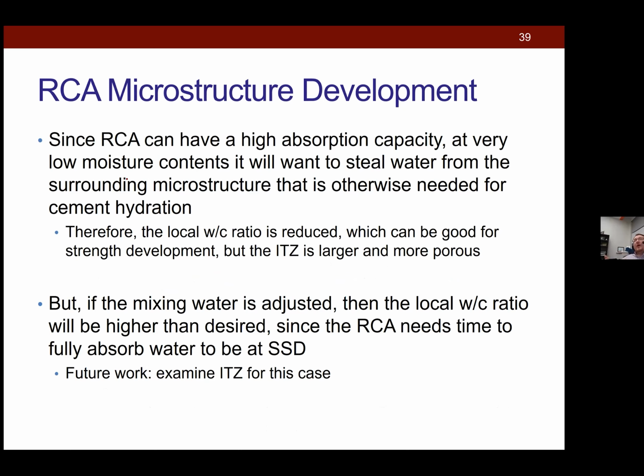Okay. The other problem is if, let's say, your RCA is completely dry, right, and it wants to absorb, let's say, 9% moisture. If you mix that RCA dry into your concrete and then adjust your batch water, the problem is RCA doesn't absorb all that moisture that quickly. Okay, so studies have shown that it might take 24 to 48 hours for RCA to become fully saturated. So it's kind of a useless method then to try and just adjust your mixing water, because now you're just changing your local water cement ratio. You're actually going to be reducing your strength, right? So here again, we can't necessarily carry on with the same assumptions for conventional concrete as we do with RCA.